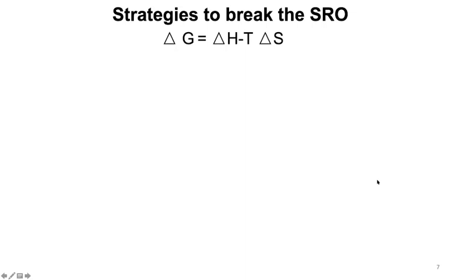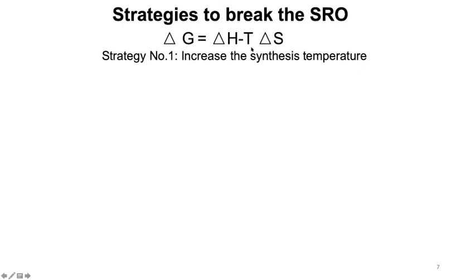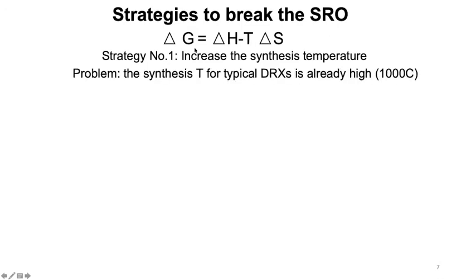We start from basic thermodynamics. Delta G equals delta H minus T delta S. We want to minimize delta G so that there can be less short-range order. Obviously, there are two strategies. First is to increase the synthesis temperature so that this term becomes more negative and the delta G can be reduced. However, as demonstrated by previous study, the synthesis temperature for typical DRX is already very high. It usually reaches around 900 degrees C or 1000 degrees C. So there is really not much space for us to further increase the synthesis temperature.